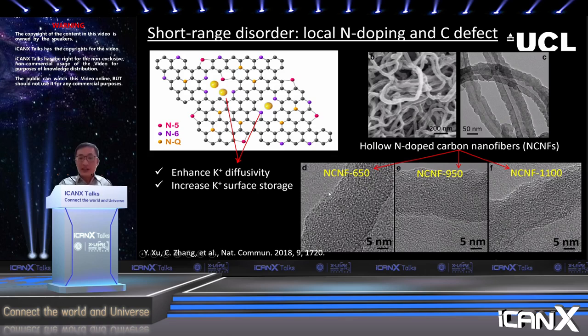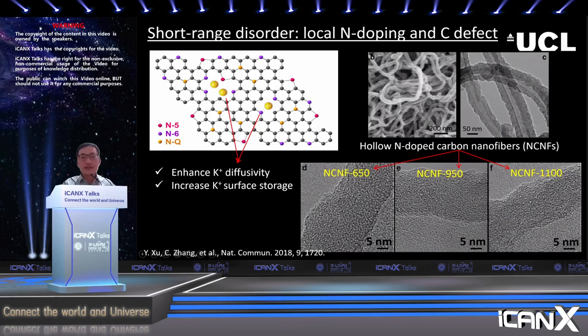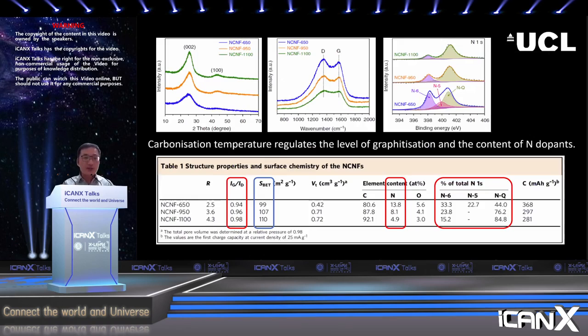As you can see from the HRTEM images, the three samples actually showed different levels of graphitization, which means they have different levels of carbon defects. We used various characterization technologies to identify the relationship between the carbonization temperature and the level of graphitization.